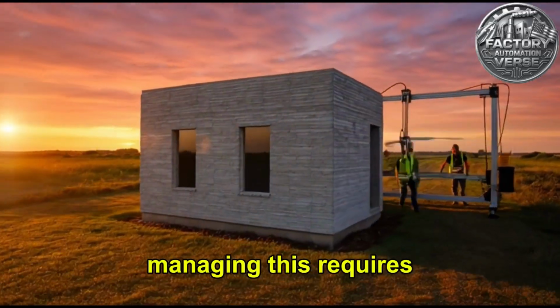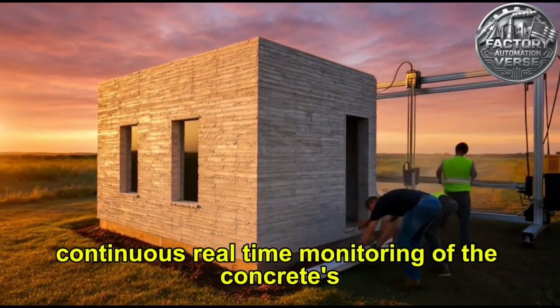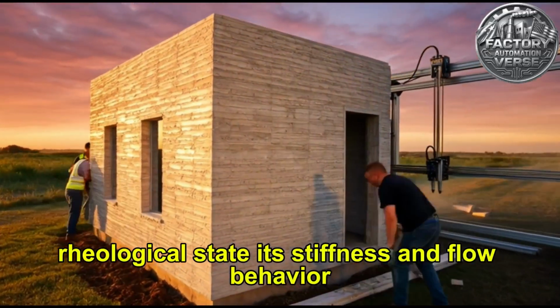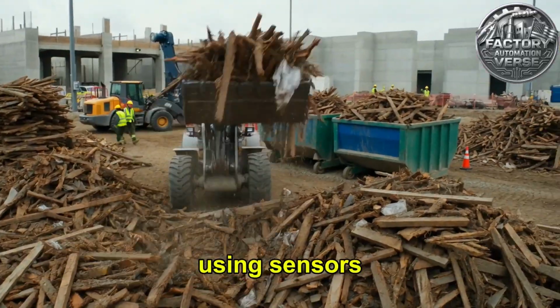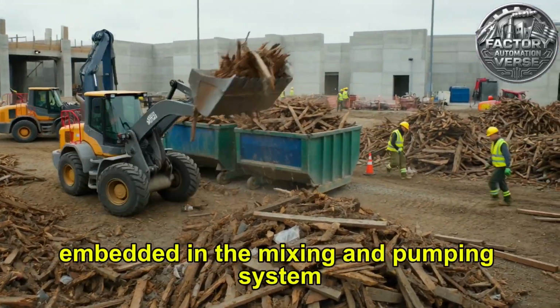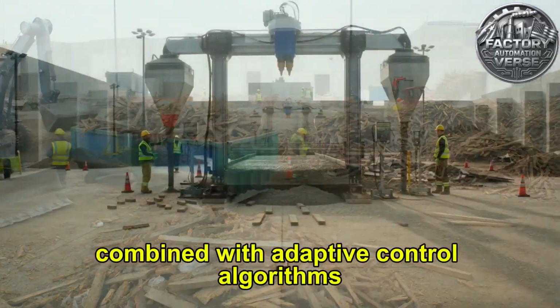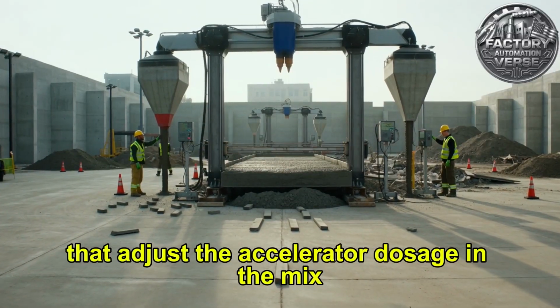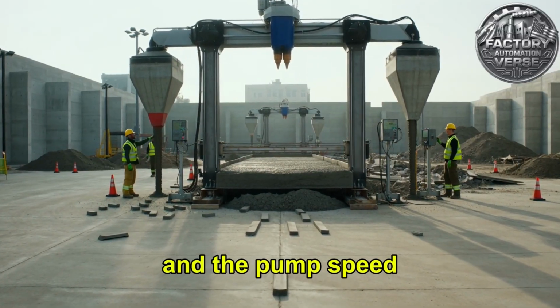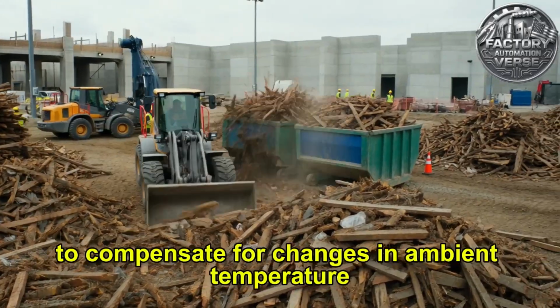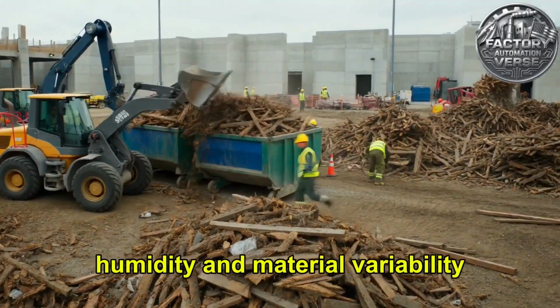Managing this requires continuous real-time monitoring of the concrete's rheological state, its stiffness and flow behavior, using sensors embedded in the mixing and pumping system, combined with adaptive control algorithms that adjust the accelerator dosage in the mix and the pump speed to compensate for changes in ambient temperature, humidity, and material variability.